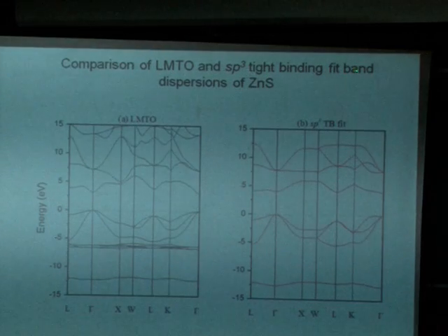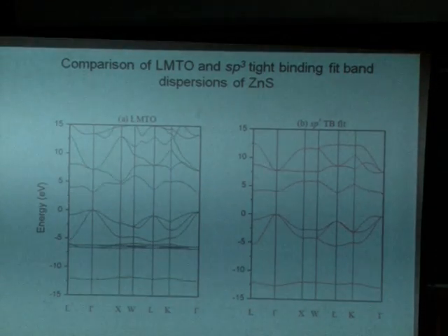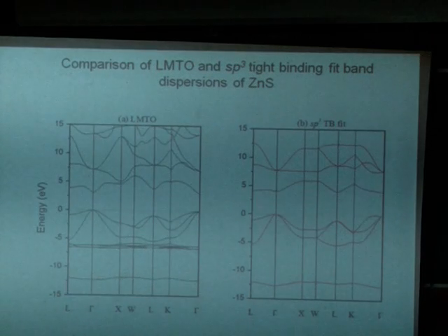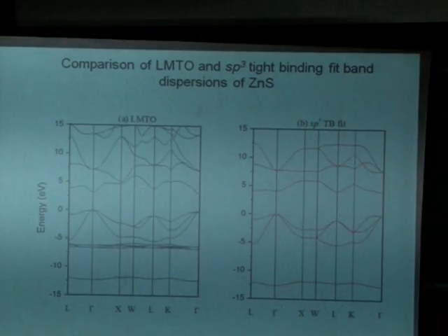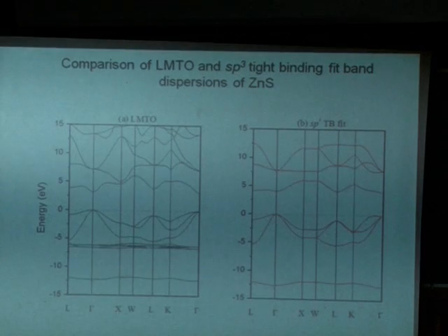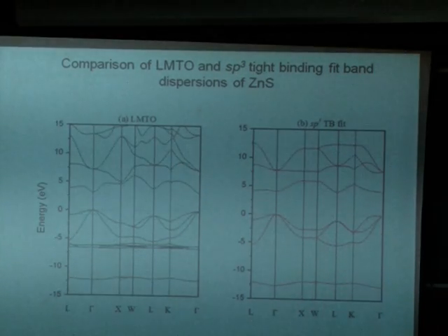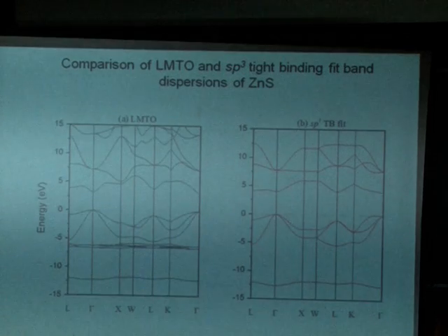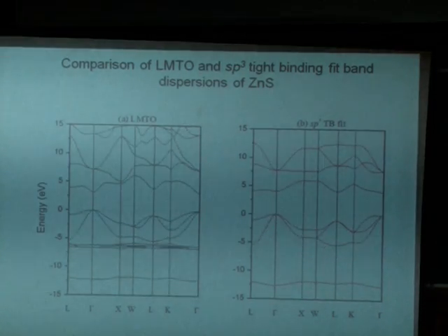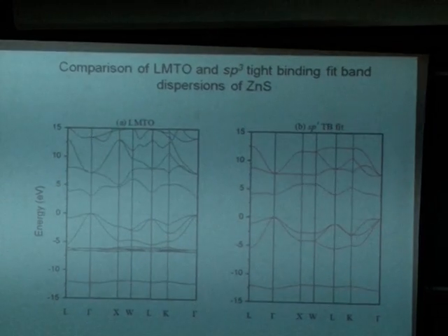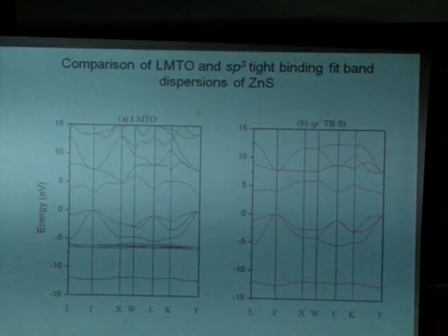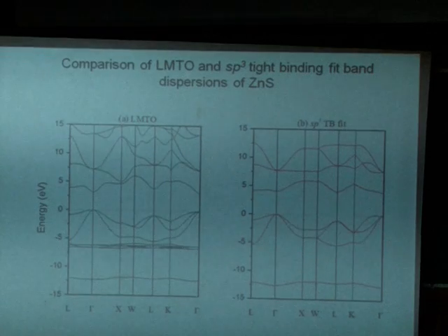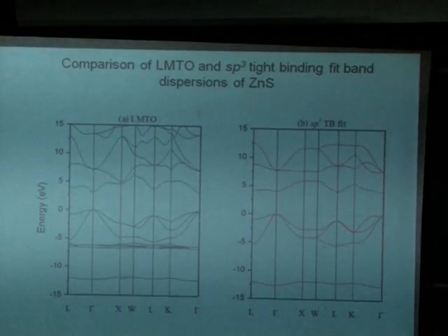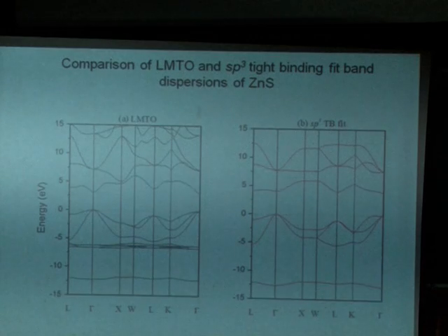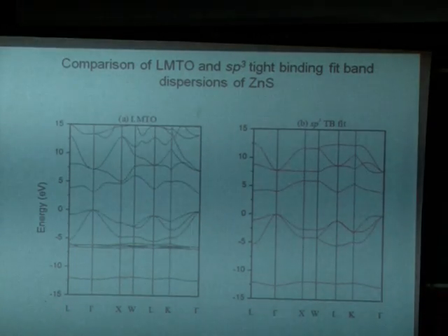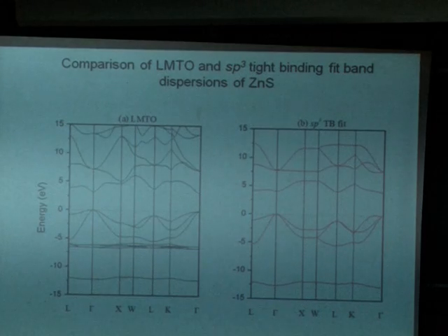Basically the reason was that we were making zinc sulfide nanoparticles and we wanted to get a transferable set of parameters. So our attempt was to start with parameters that simulate the bulk correctly and then use that in a real space calculation. We needed to do tight binding, otherwise the number of atoms we were trying to handle, 10,000 atoms, would be impossible. In tight binding you can do that, but otherwise you have to evaluate those integrals, which is key.